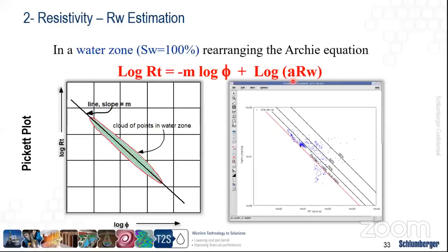As I said before, A is assumed to be 1, so typically this is just log RW, which means in order to transform this into an equation of a straight line and plot it, we need to plot it on a log-log scale. So what we plot is the log RT. This is a log-log scale. We plot RT on the y-axis and phi on the x-axis. And the slope would represent what we call m, and the point of intercept, which typically happens at log phi equal to 0, would represent the RW. And this is only applicable when we have a water zone.